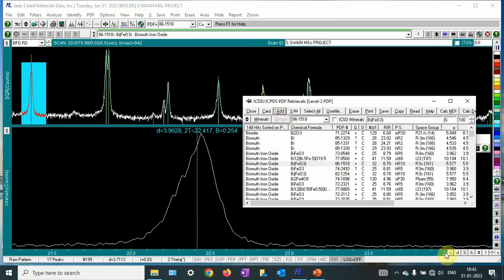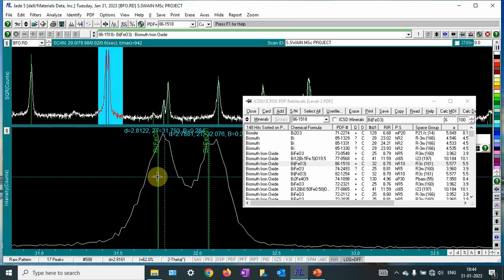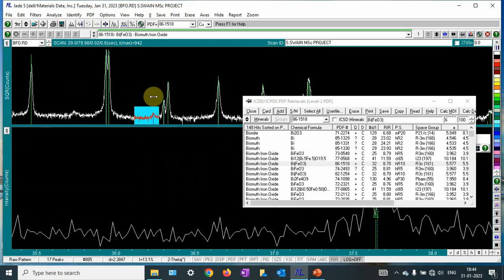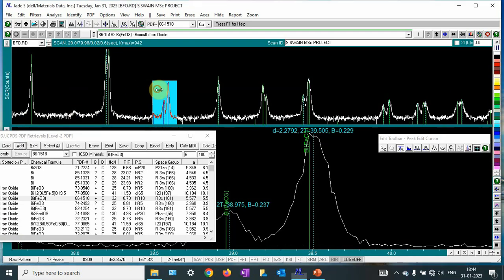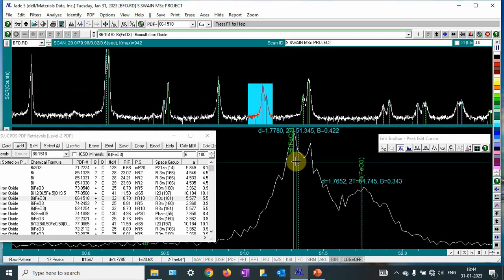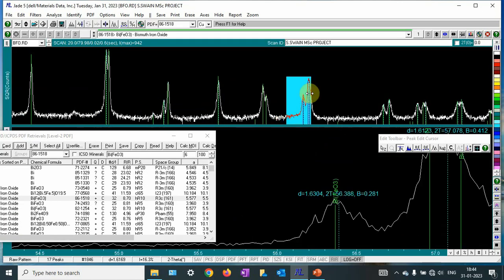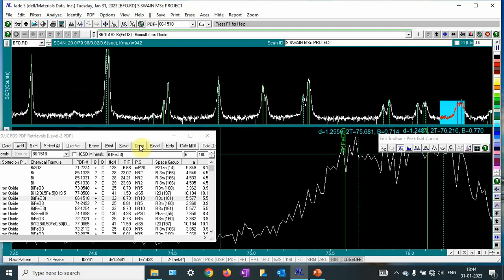If you add it, you can see this is the bismuth ferrite phase and this is your own pattern, so they are basically matching. This is the experimental, this is theoretical, so mostly they are matching, right? You can see that this data conforms to the bismuth ferrite data. This blue line and this experimental data are matching. So I confirm that the phase identification is complete.